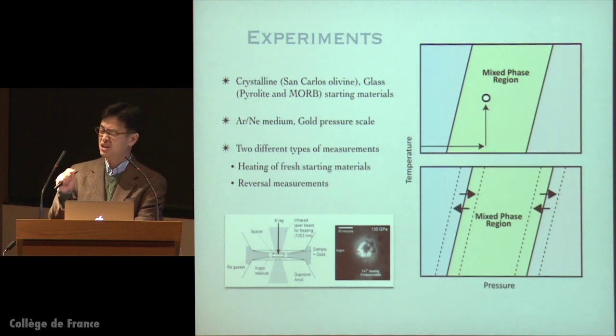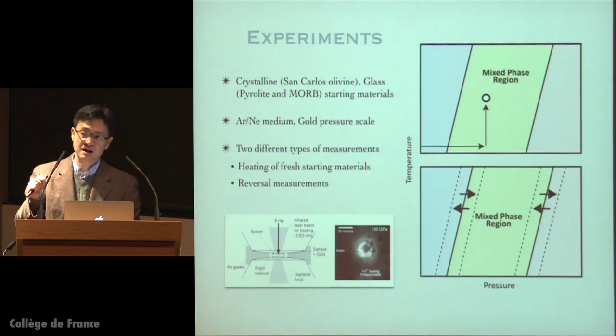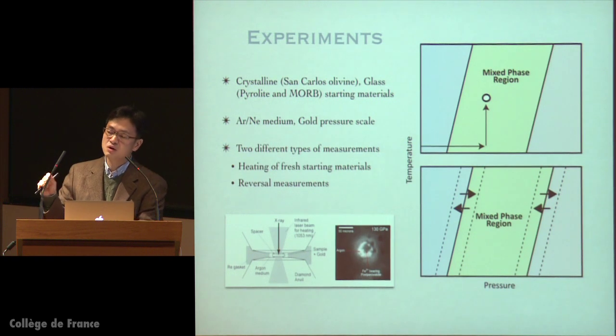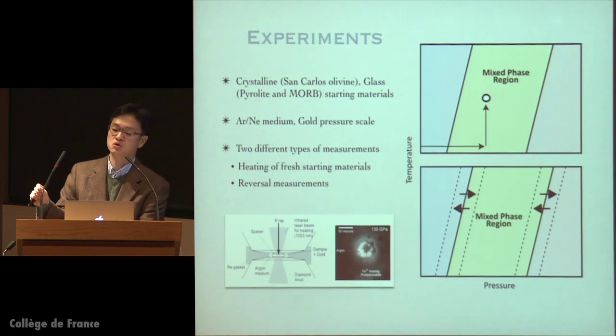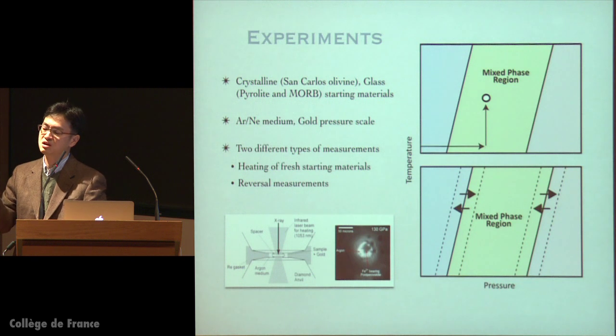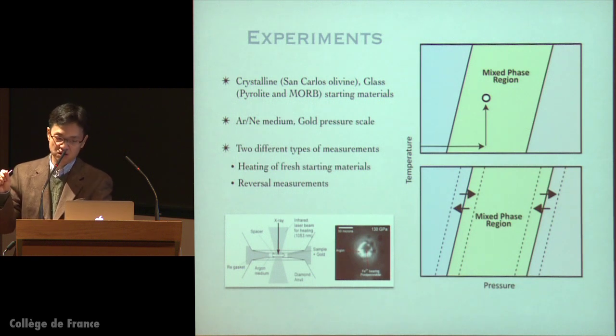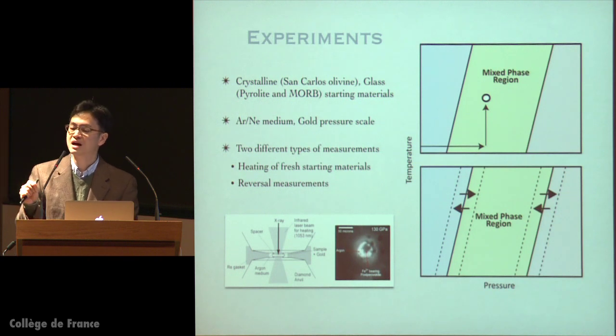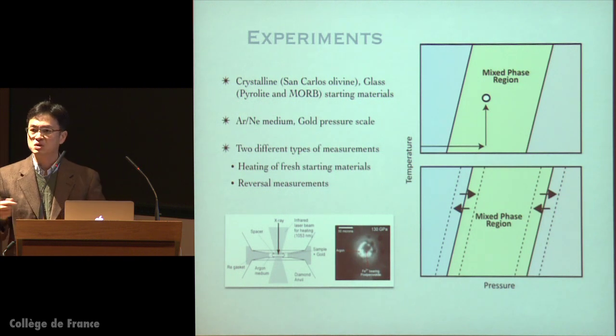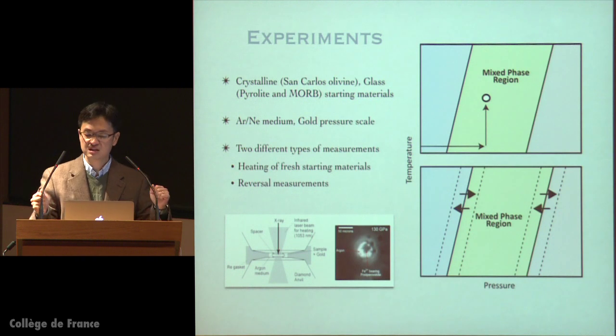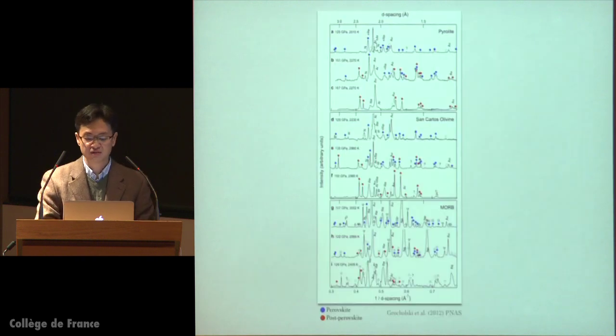But over the years, we mineral physicists have learned that in case you have some thermal gradient and pressure gradient, this doesn't necessarily give you the most stable phase you expect. Rather, it could give you the metastable phase. But nevertheless, we decided to take these two approaches and see what type of results we get.